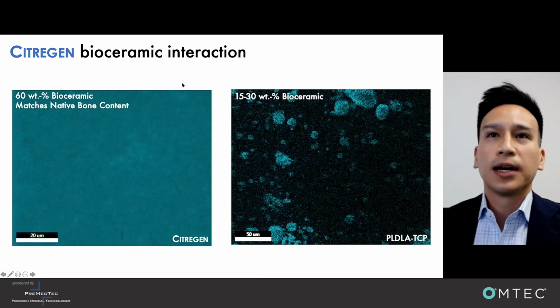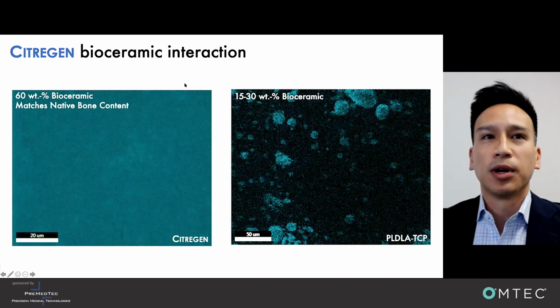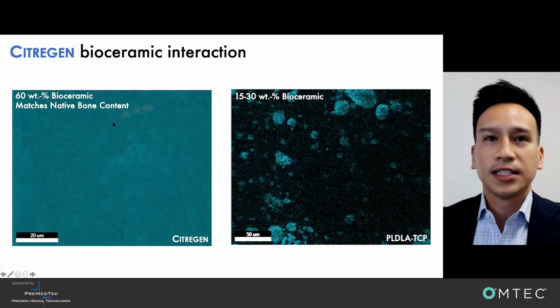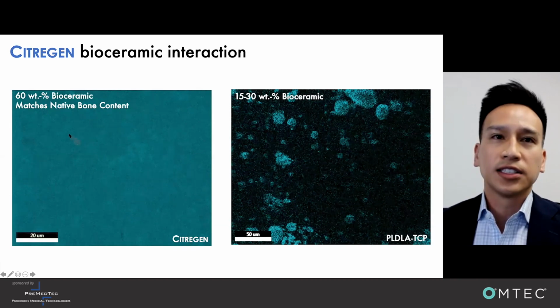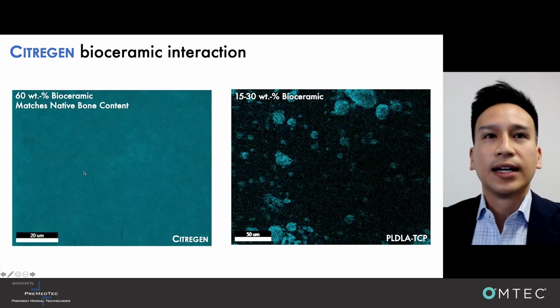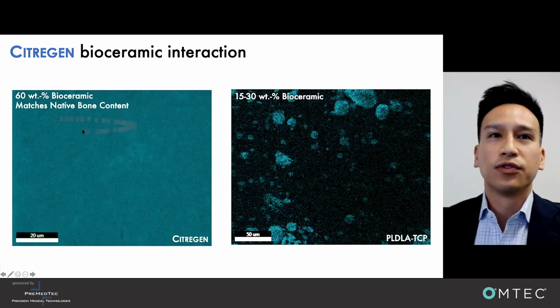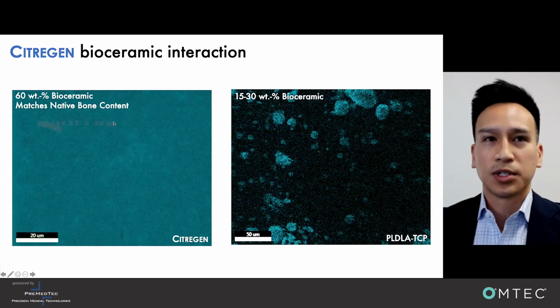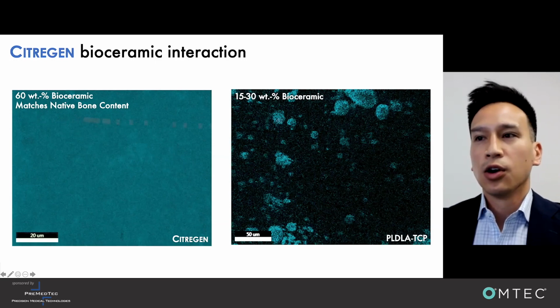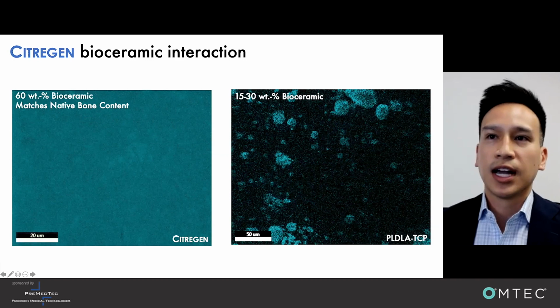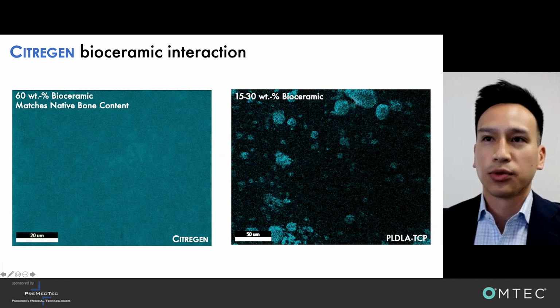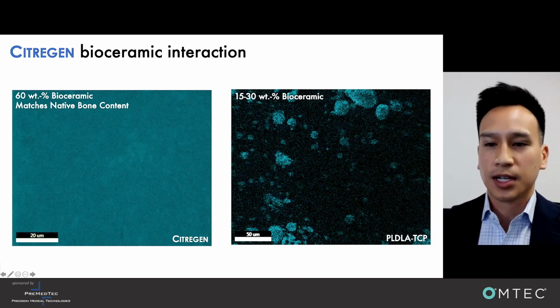Citregen also has some bioceramic interaction due to the citrate molecule. You can see SEM-EDX pictures here where calcium is stained in blue. You can see the Citregen material has a very uniform bioceramic content, with up to 60% to match the native bone content, whereas PLDLA TCP materials have agglomerations of TCP and bioceramic and can only be loaded up to 30% before becoming brittle.